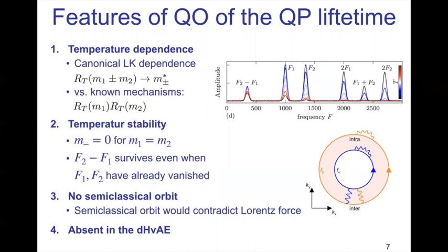It's not allowed. You cannot take it in these metals. So if you think about these difference frequencies, we cannot think about a semi-classical path which induces them, but it's purely a modulation effect coming from the quasi-particle lifetime.